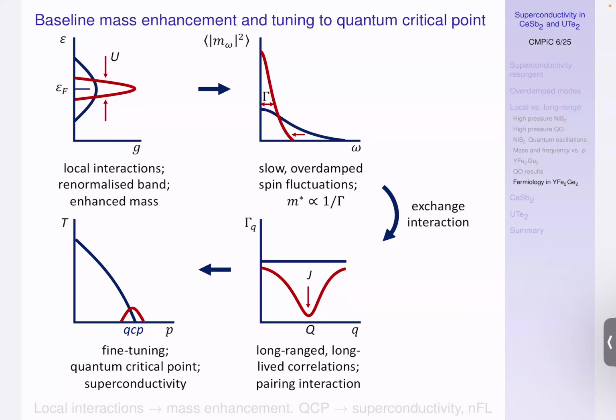On top of that, you are usually close to the threshold of magnetism, so you get an exchange interaction between neighbors, which will drive instability. So at an instability, this fluctuation rate, which is already low, can go towards zero, can become even smaller. And it introduces dispersion into the picture, and if something is strongly dispersive in Q space, it gives long range in real space. So you can get longer range and long-lived correlations, which can provide a pairing interaction and then superconductivity.